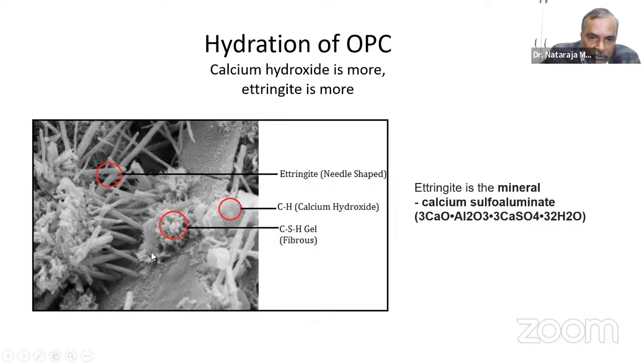In that area, how much is the distribution of the CSH? Calcium silicate hydrate gel is actually the strength forming compound. It really adds to the quality of the concrete. It adds to the strength of the concrete. When the OPC hydrates, we also should know that calcium hydroxide is liberated. This calcium hydroxide is not a good material. It reacts with carbon dioxide, and on further reacting with carbon dioxide, you have calcium carbonate and calcium bicarbonate, which leaches out of the concrete. Because of this, the concrete becomes more porous inside. That is where the durability of the concrete over time becomes questionable.